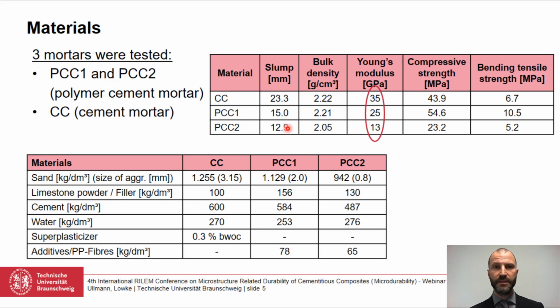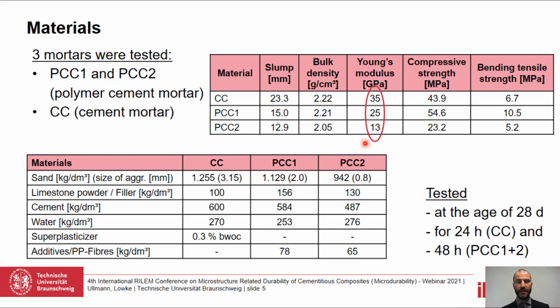next to some differences in the compressive strengths, we also have a very broad range of the Young's modulus. And that was our goal, to use materials with a broad range of the Young's modulus in order to point out certain effects that are caused by the Young's modulus on the later on tested dependency on external loading. The tests were conducted for 24 or 48 hours, dependent on the material, and after 28 days of curing.